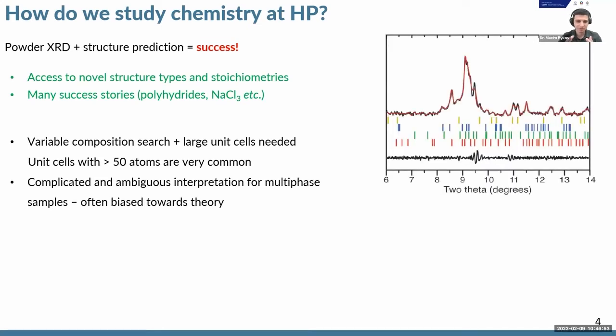However, it's still limited to quite simple compounds, and it is common that in high pressure synthesis we have really complex structures with more than 50 atoms in the unit cell and multiphase products. In this case, the analysis of such experimental powder diffraction patterns becomes very ambiguous and usually biased towards theory. Once you start throwing more and more phases to fit such a diffraction pattern, you of course get better residual values, but it doesn't mean that you get a correct result.